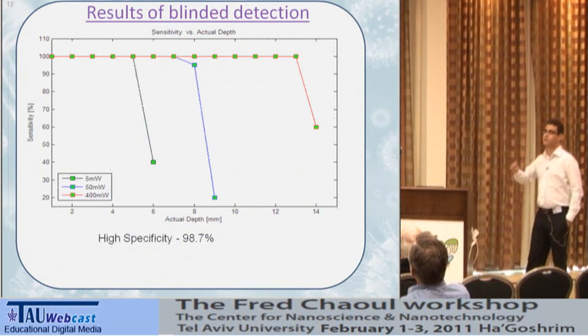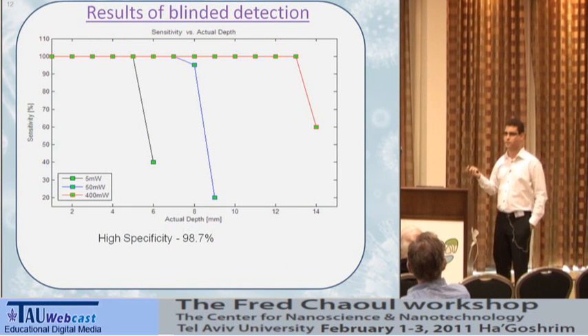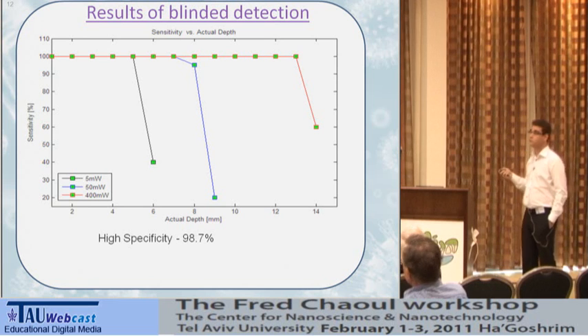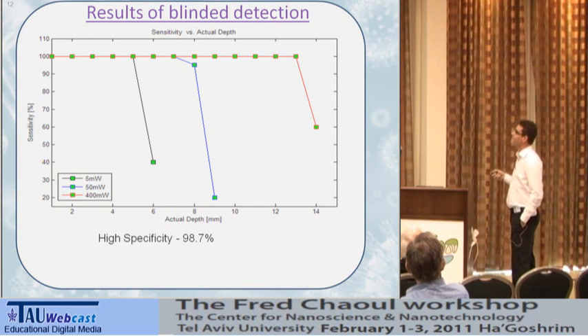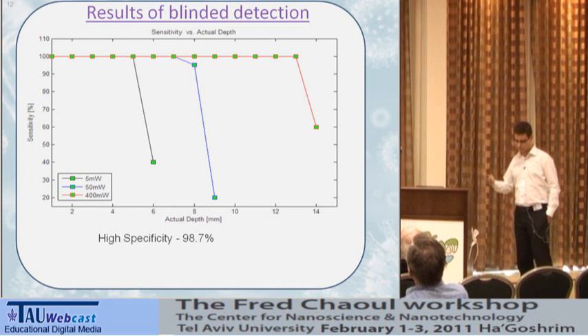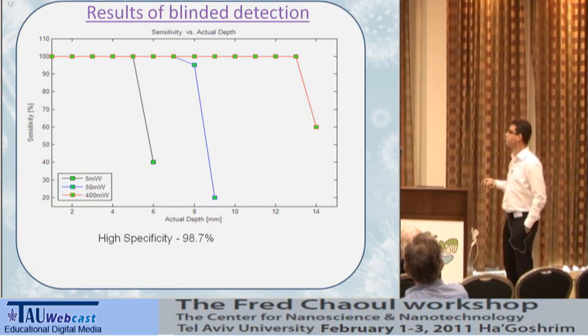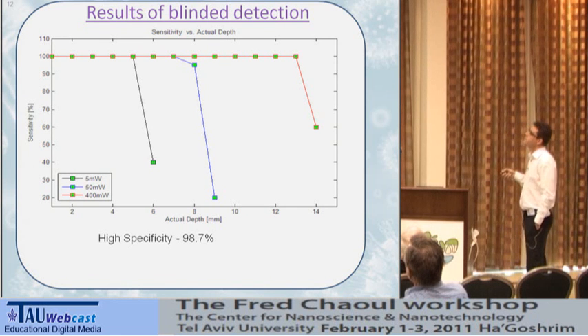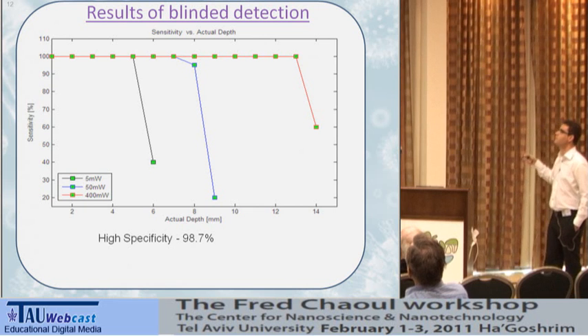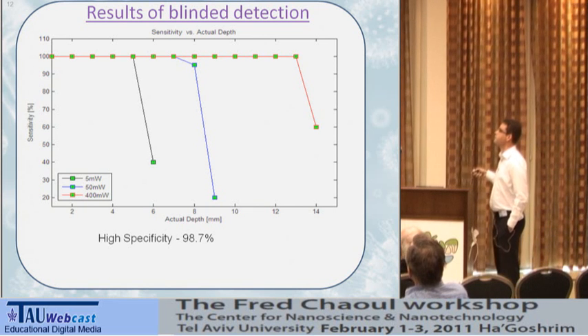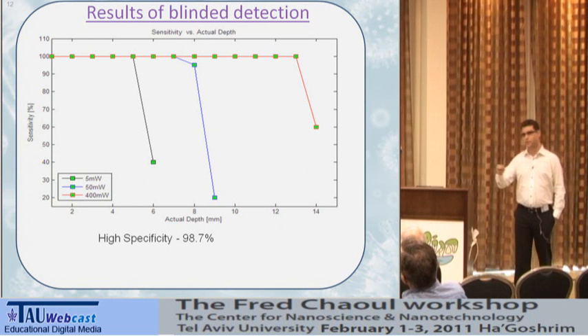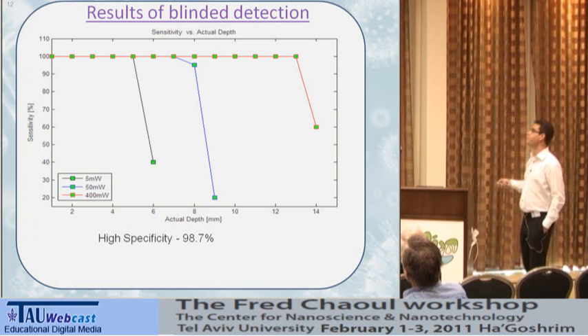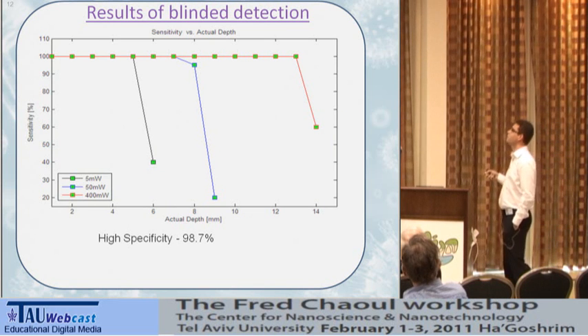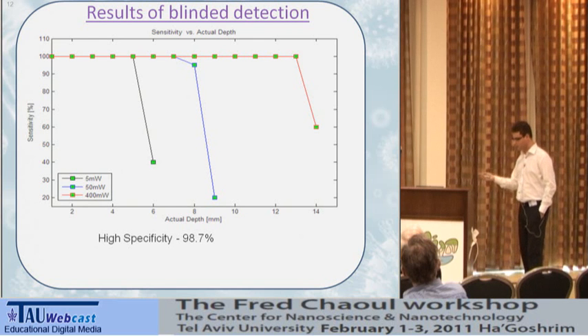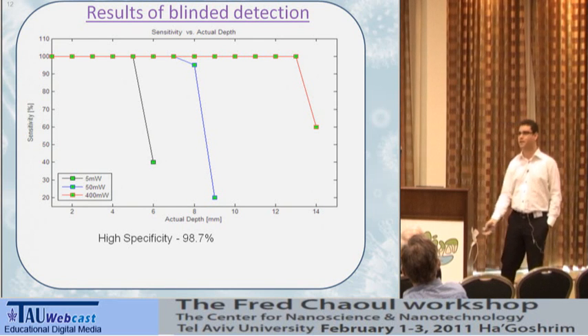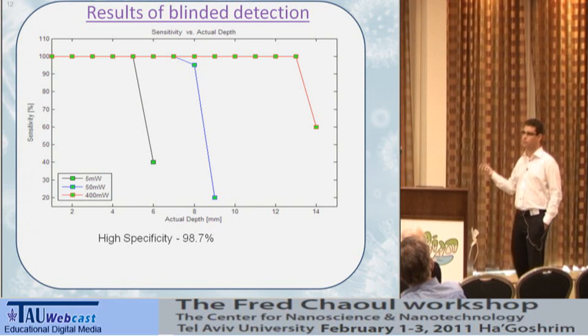Also, we did a series of blind tests, and we tested sensitivity and specificity. Okay, what we can see here, we tested it for a different amount of heat that we deliver to the tumor phantom, and what you can see here is that it's virtually 100% until some threshold, and then it drops down to nearly zero. So it means that for every amount of heat that we inject, that we deliver to the tumor, there's a finite threshold, finite depth that we can detect. Any tumor that is deeper than that, we won't be able to see it.